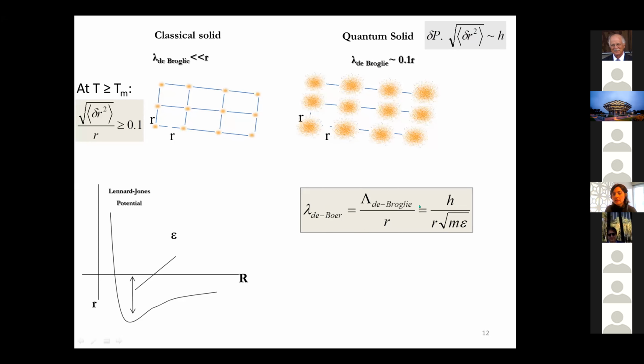And as you can see, this de Boer parameter is proportional to a few things. h is the Planck constant, which is not going to change. But things that can change are R, which is the interatomic distance, or the potential depth, the mass, and also the type of interactions that we have. Obviously, the type of interactions are also always proportional to these distances. And now, for every high pressure person sitting here, we can immediately see that this quantumness can be easily tuned, because both R and E depend on the distance or density. Pressure is a wonderful tool to adjust this de Boer parameter.